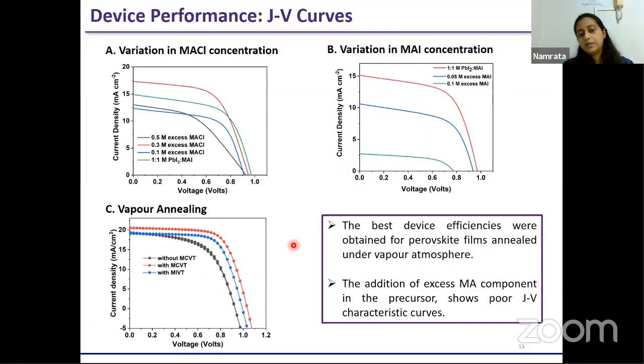Next, we fabricated the entire device and compared the device performance, particularly the JV curves, for each corresponding condition. We observed that while we vary the MACl concentration in the perovskite solution, we get the best performance when we have 0.3 molar excess MACl. And when we vary the MAI concentration, we find that a 1:1 stoichiometric ratio is the best, and we don't need excess MAI in our precursor solution.